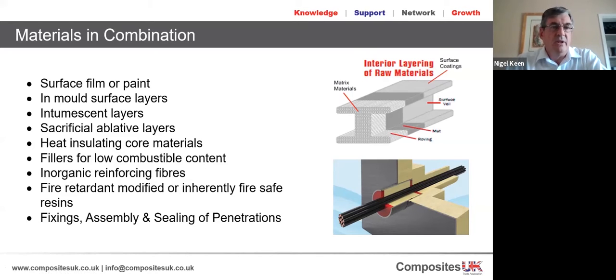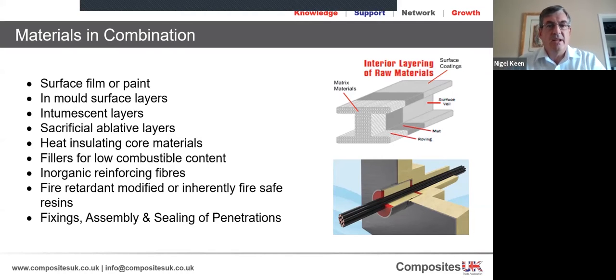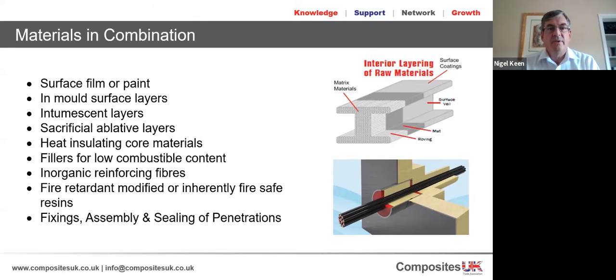And often we're using inorganic reinforcing fibers rather than thermoplastic or carbonaceous ones, and they can be essentially fire resistant. So the more glass, for instance, you've got in a product, the higher glass content, the less organic matrix you have to burn. Finally, you can actually modify your material, so you can have a resin system that is inherently fire safe, that produces a lot of char that's very difficult to ignite or burn, or you can modify it in some way. You can add additives, you can really play with the matrix system to help you with fire.